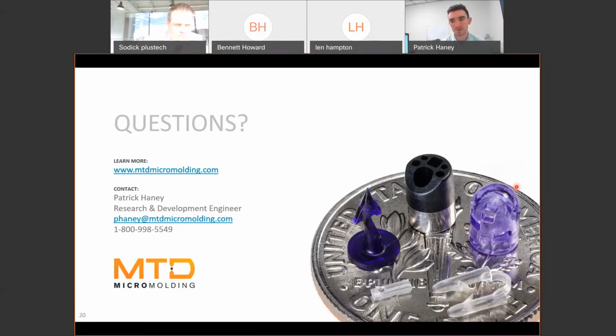There are other polymers that are challenging, like fluoropolymers can end up being very challenging because of how corrosive they are, and because of the extended shear rates that we expose our stuff to. Sometimes off-gassing can be more of a problem for polymers that tend to behave like that. High performance polymers like PEEK or PEI, their characteristics depend heavily on their level of crystallinity. You can imagine if you have such a small part surrounded by so much relative tool steel, you'll suck the heat energy out of that immediately. So when it comes to something like crystallization, that's a thermodynamic phase change. When we suck the heat energy out as fast as we do, sometimes those crystallization phase changes don't have an adequate amount of time to complete.